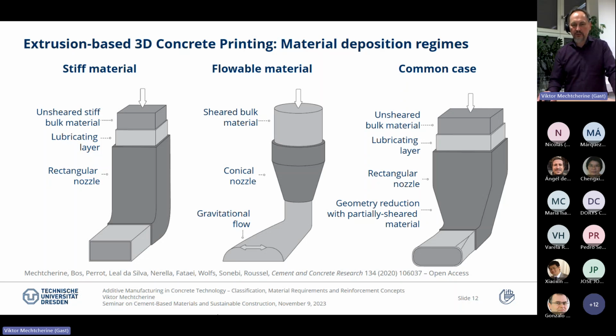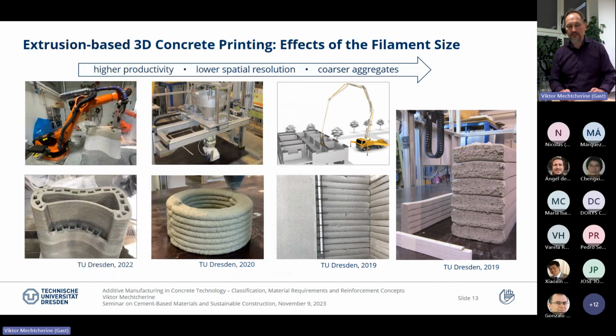Good. Another distinction we can make is by filament size. In many cases, we go for fine filaments to have high resolution, to be free in shaping the material to whatever form we want. This is what you see here on the left, where the resolution also provides some voids, which we maybe can use for different functions, like putting in cables or whatever. Then what you see in the middle is a little bit coarser printing, but often also practiced in construction. And then on the right side, our specific approach in Dresden, where we use coarse aggregates, very coarse or thick filaments. In this example on the right, you see filaments with a width of 150 millimeters and a height of 50 millimeters.